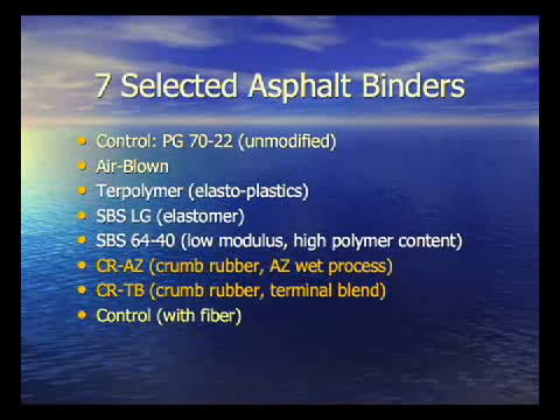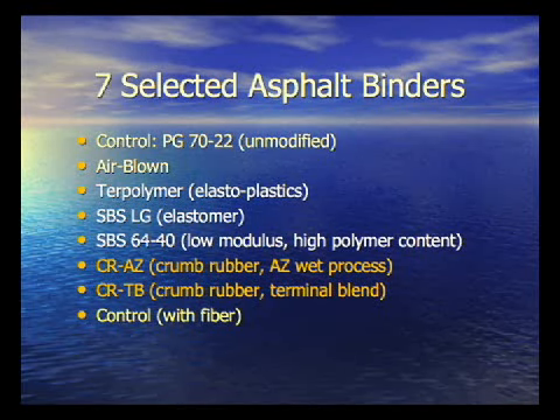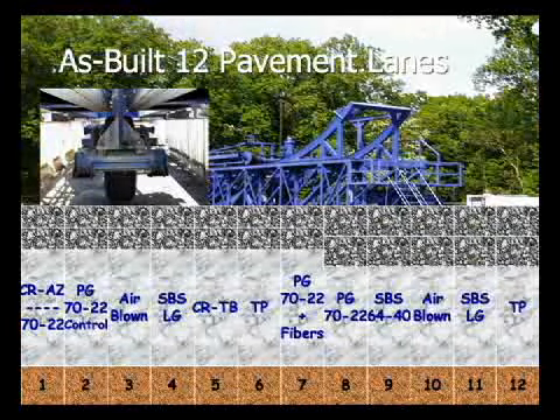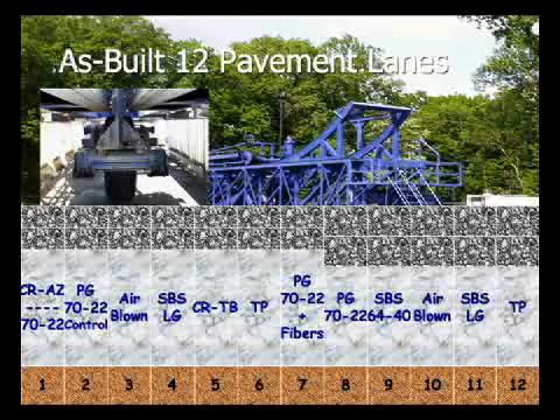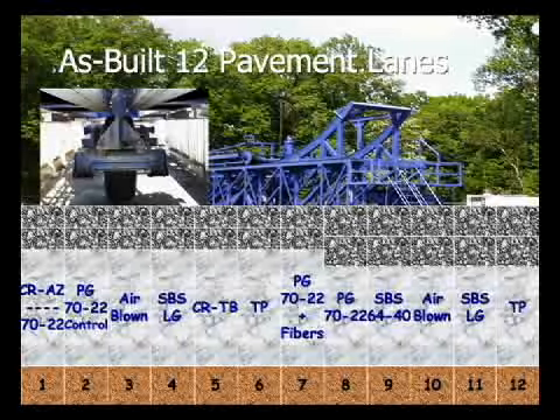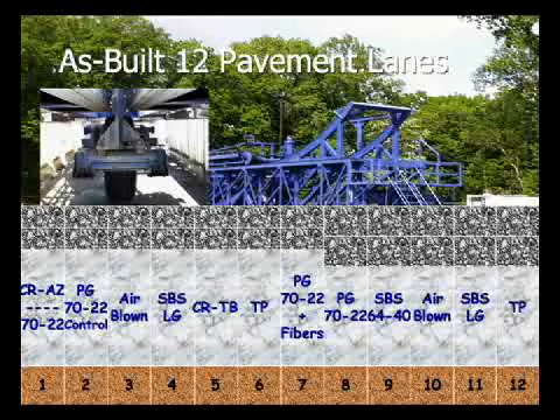I'll talk about the binders which were selected. Essentially what we've got is an unmodified control, an air-blown binder, one with an ethylene terpolymer, a linear grafted SBS polymer, and one which has SBS, but it's a very low modulus, but also has a high polymer content. That's also nicknamed 64-40. We're looking at definitely the Arizona wet process, also the terminal blended crumb rubber, and also a control mix with fiber. All of these binders, the target was to bring them up to the same PG. That way, if they have ideally the same PG, they should all ideally perform the same. And that's not the case, as we can see here. And that will give us excellent ground truth, which we'll base new binder specifications from.